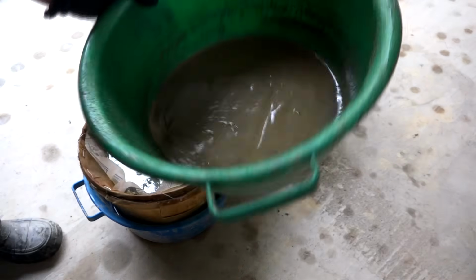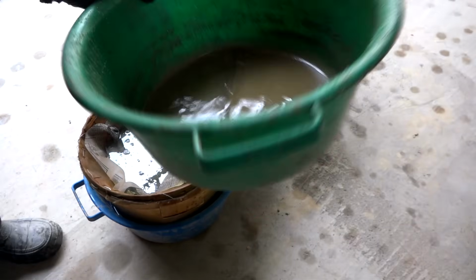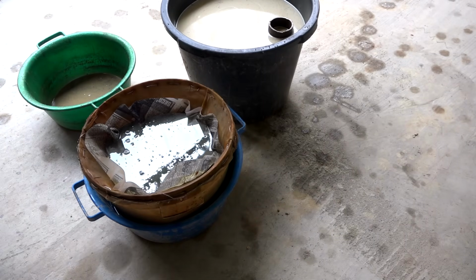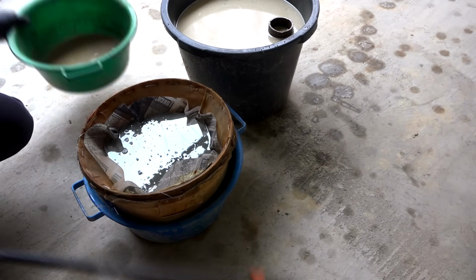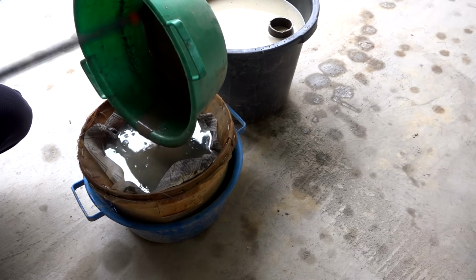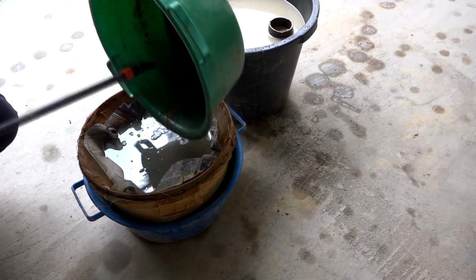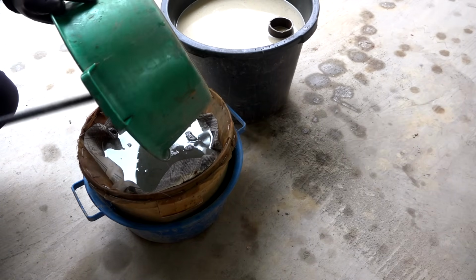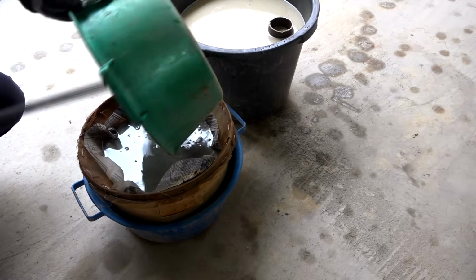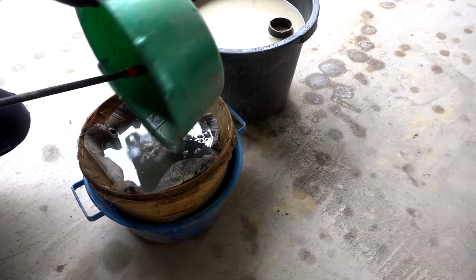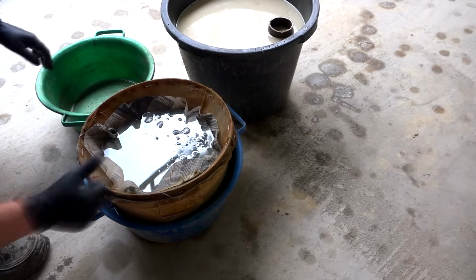I see many yellow particles, most likely gold particles. As the foam settles, the larger particles settle back to the bottom of the container, but after filtration, everything will remain on the filter. I carefully wipe the container that held the flotation foam with a napkin, particles of the precious metal are stuck to its walls.